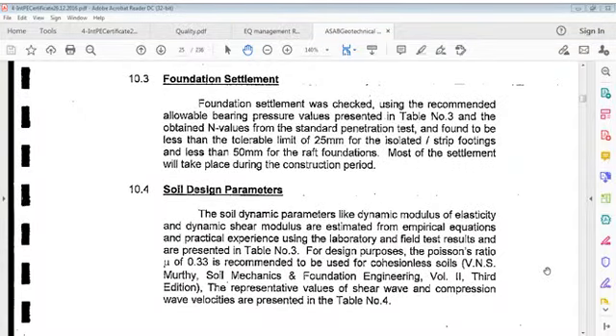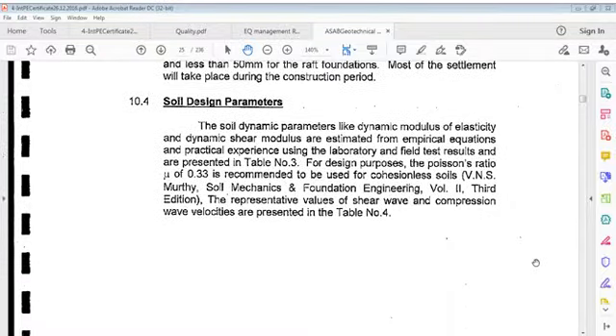Foundation settlement. Foundation settlement was checked using recommended allowable bearing pressure values N-values obtained from standard penetration tests and found to be less than tolerable limits of 25 mm for isolated strip footings and less than 50 mm for raft footings. Raft foundations. Most of settlement will take place during construction period.